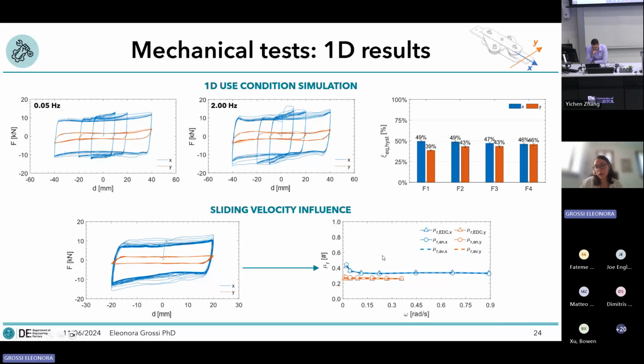The lines with the triangular marker I computed the coefficient of friction starting from the energy dissipated per cycle, while the circular marker I computed from the analytical formulation, and the dashed line is just the average between the two. You can see that independently from the methodology, I achieved the same number, which is quite promising. And also that the number that I obtained, which is around 0.4, is the same that I obtained from the tribological test, which is good.